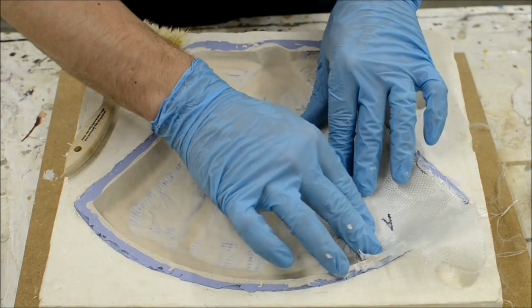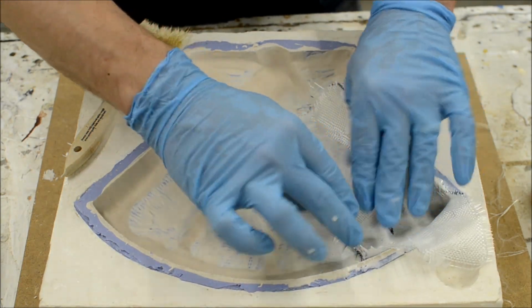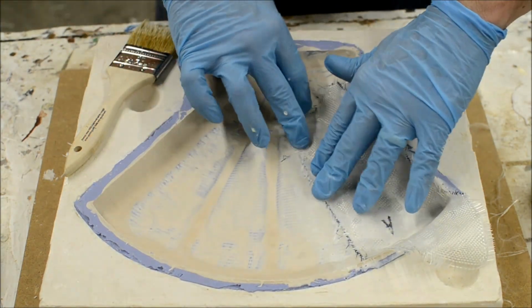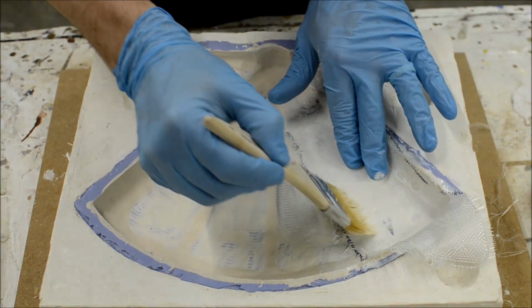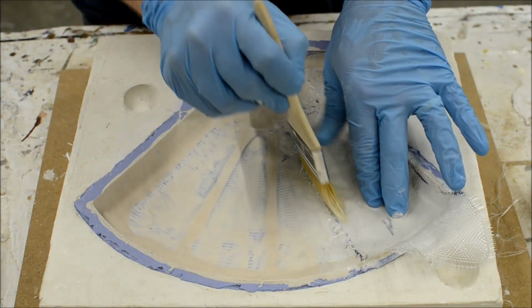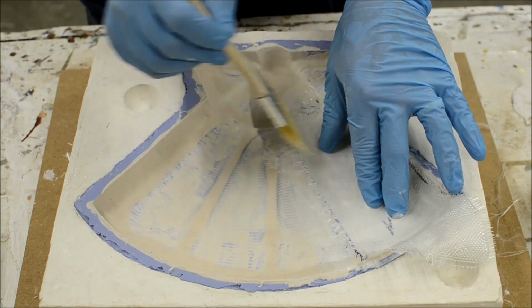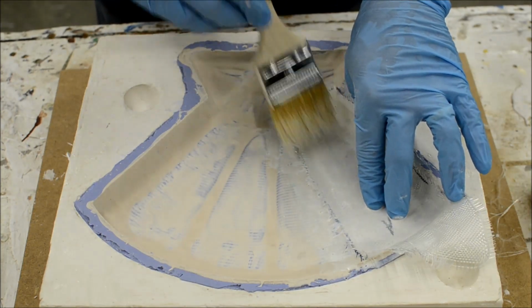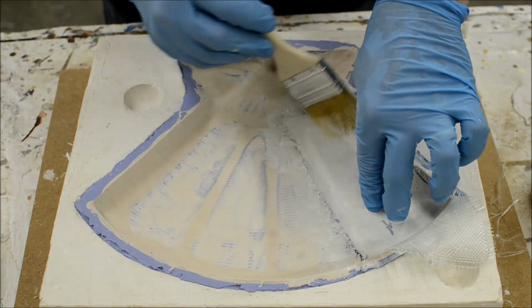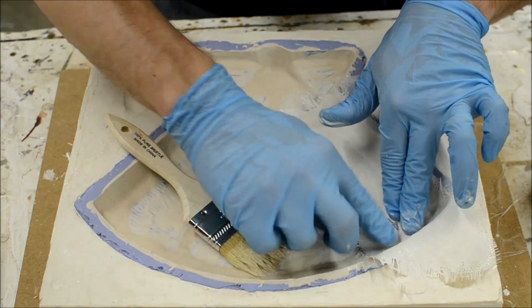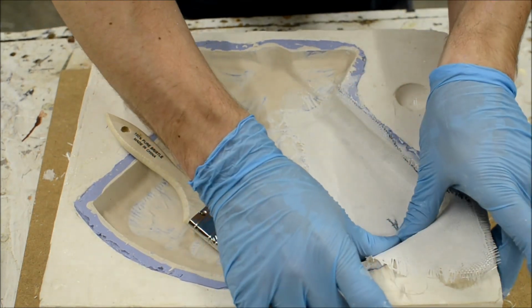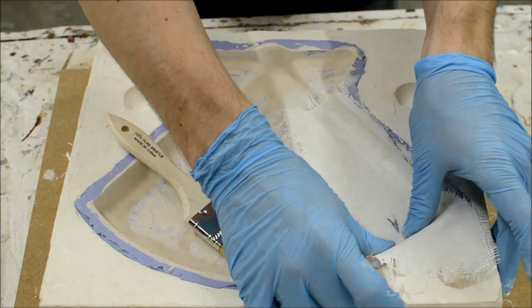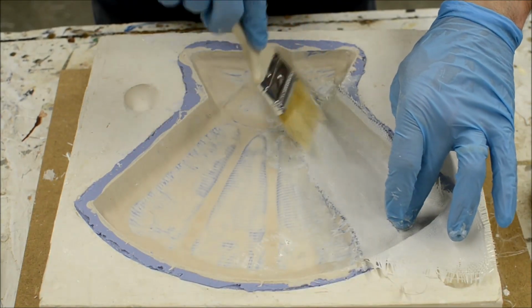Lay your pieces over the entire surface of your mold, with the edges slightly overlapping each other. Brush or roll more resin over the surface of all the cloth until it is fully saturated. Press out any air bubbles that get trapped under the cloth. A dry, stiffened brush can be helpful for this task. For larger areas, use a roller.